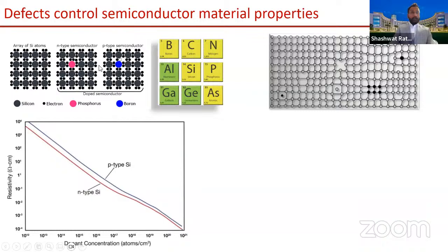So if you use phosphorus, it's known as an N-type semiconductor because you have excess electrons, and in a P-type silicon, you have excess holes in the lattice. So essentially, by changing the dopant concentration, you can change the conductivity, or the inverse of resistivity, by orders of magnitude, as you can see in this plot.